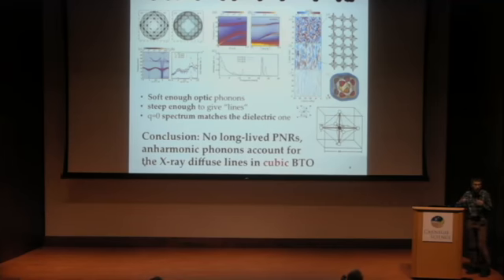We can also look at the histogram of the displacement of titanium. Really, in the cubic phase at that temperature, which is 100 Kelvin above TC, I forgot to say, there are 8 positions which are more probable, the most probable positions of the titanium. It's off-centered. But if you look at how many of the titaniums are in these positions, only 5%. So 95% have energy which is over the barrier between them, so they are everywhere around. So most of the titaniums are just running around, so the barrier is very small.